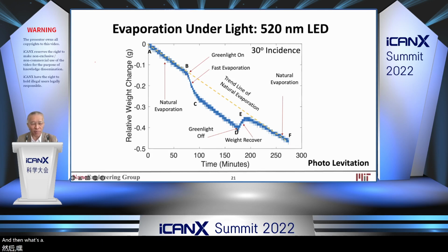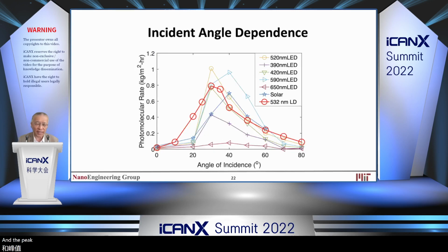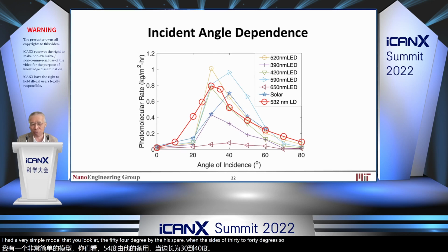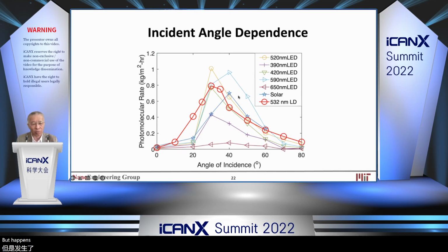And then what's amazing is that when you turn off the light, the weight recovers. So it's like a light lifts up a bucket of water and puts it back when you turn off the light. We call this a photo levitation. And really interesting to us. And the peak, it has an angle dependence. If it's a lower incidence, you don't see that effect. But it peaks at 30 degrees to 40 degrees. In fact, I told Jiandong, I had a very simple model. I said we should look at 54 degrees, but the experiment saw it's 30 to 40 degrees. So we do not understand this yet. But it happens to visible light. And once you go from green to the red light 650, you can see the effect is very small.